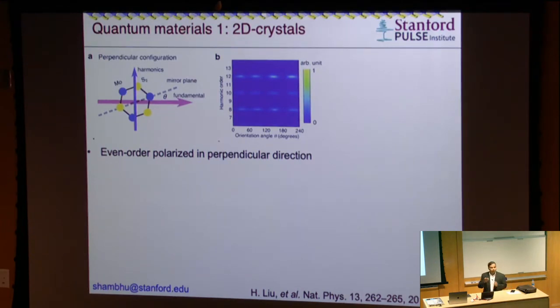We looked at the polarization of these even-order harmonics. Usually the harmonics have the same polarization direction as the laser field. This is how things are understood in the gas phase, because there is no dipole to radiate in the transverse direction. Here we found that these even orders are completely orthogonally polarized to the laser field. So there was something unexpected, and it took some time for us to understand.